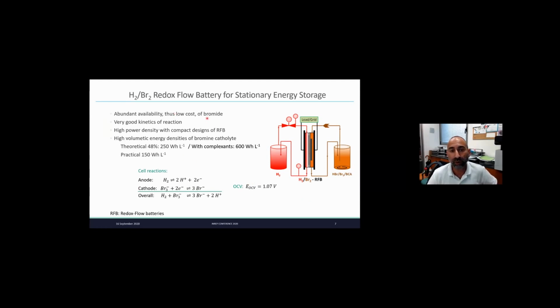So the low cost of bromine is one thing, but the really good thing about bromine is the good kinetics of reaction. You can go from tribromide to bromide without any catalyst. You just need carbon, and the reaction is very fast. On the other side, you need also to catalyze the reaction of hydrogen to proton to hydrogen. In that case, it should be a piece of cake, because there are a lot of materials doing that. We know about platinum, we know about iridium, we know about ruthenium. The problem is that these materials are pretty expensive and not abundant, and also they are very, very sensitive to corrosion, because we have some corrosion.